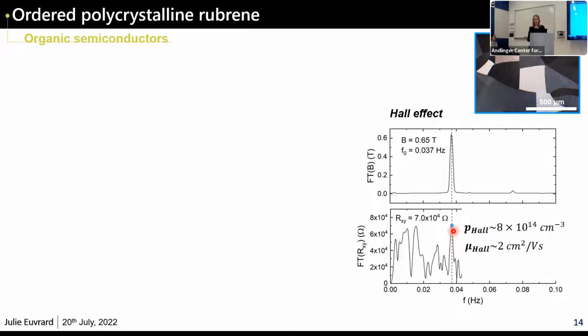And when you calculate values out of the signal, you can calculate the density of carriers, how many carriers you have, and the mobility, so how fast they can travel. And what we see is that those values are fully consistent with what we expect. So this tells us that transport is most likely band-like in this polycrystalline film.